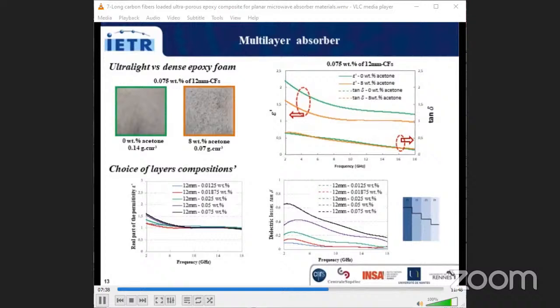This decrease in permittivity increases the impedance matching between the air and the absorber interface. At the same time, we keep the same losses, which is ideal to realize an absorber material.